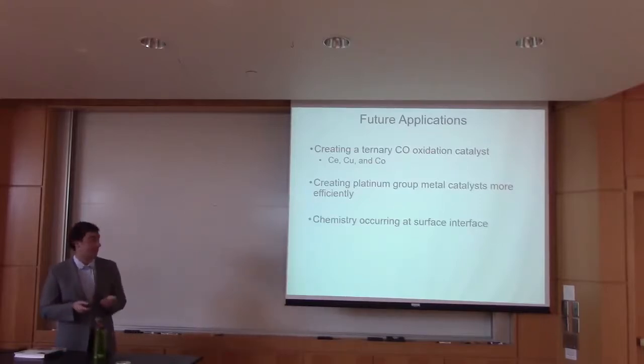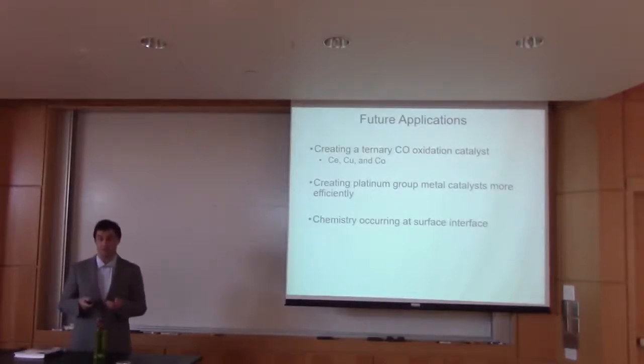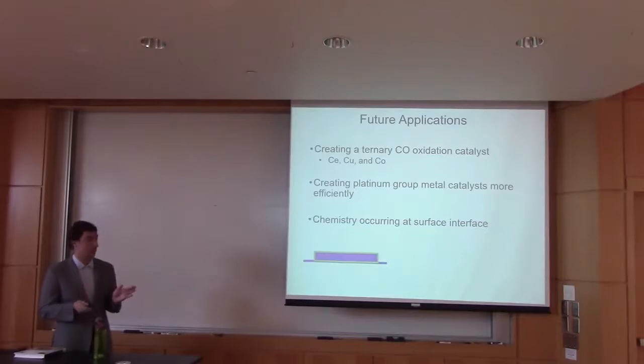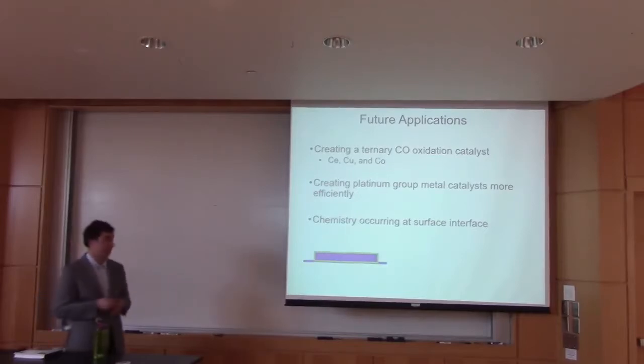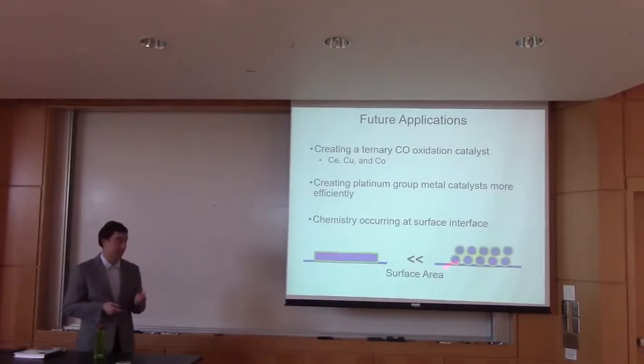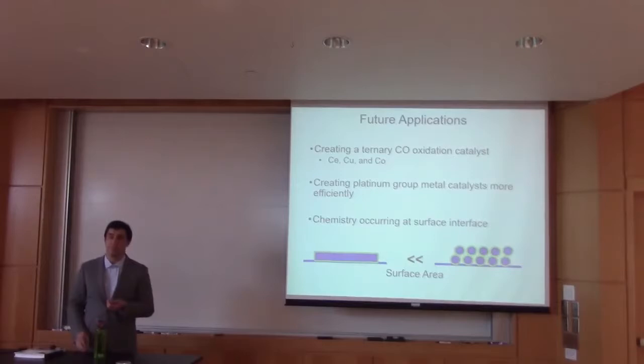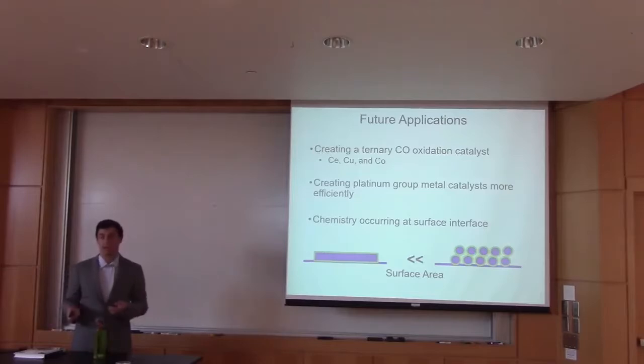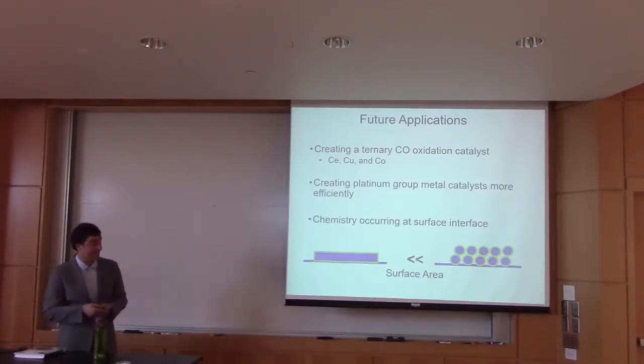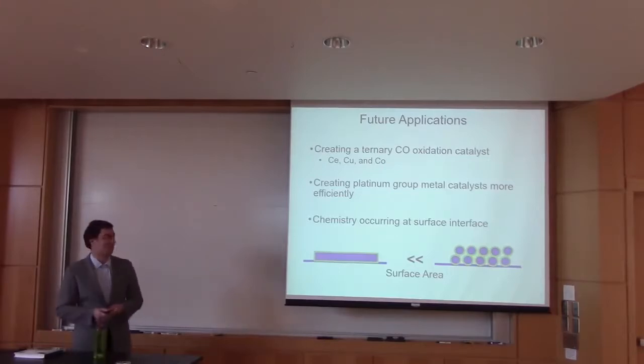And again, the chemistry we're seeing is occurring at the surface interface of these catalysts. So we want to take the traditional way to make these catalysts and create smaller nano domains through this MOF templating to give us more active sites and ultimately improve the atom economy of these reactions and of these catalysts and use less metal but get a higher efficiency, which would be fantastic. But we're currently right here, and I'm very excited to see where this goes in the future.